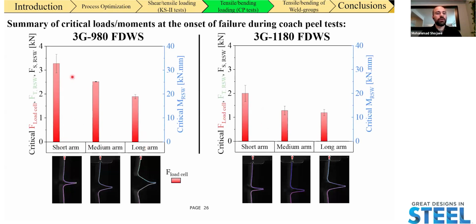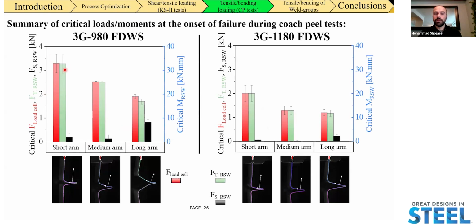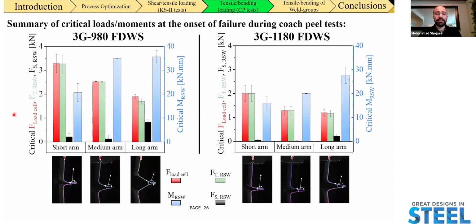As we go from the short arm to long arm, we have a decreasing trend. Same thing with the tensile component of force, but we're getting a higher and higher contribution of the shear force component, which is still quite negligible. It's less than 1 kilonewton in all cases. And at the same time, as we're reducing the effective tensile load component applied to the spot weld, as we go from the short arm geometry to the long arm geometry, we're getting a higher and higher amount of bending moment that is being applied to the spot weld at the onset of failure, which is shown with the blue bars here in these two graphs.